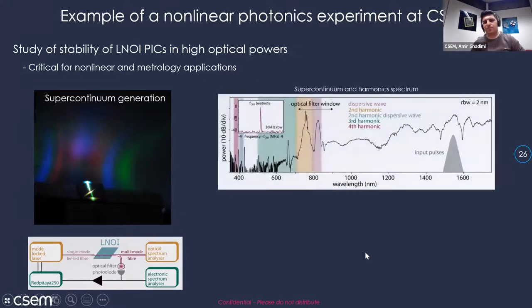If you look at the spectrum, this is a really nice experiment we recently did. This is our input pulse, the spectrum at 1550. Through this nonlinear process, you create a supercontinuum, but also high harmonics. You can generate second, third and fourth harmonics. Normally these blue lines are higher harmonics. Interestingly, your supercontinuum will beat with the second harmonic. You will generate from the supercontinuum a wavelength at around 780, but also from the second harmonic. You see in the inset the beating of these two. Again, the effect is so efficient that we can see the beat note, the f_CEO, of this mode-locked laser by more than 40 dB.